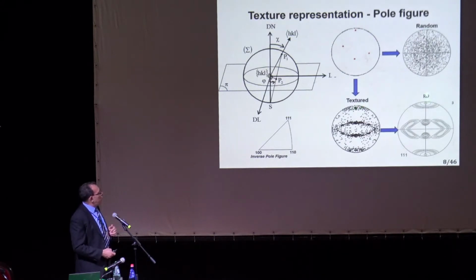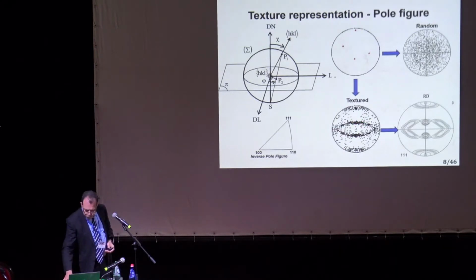For example, this is the rolling direction. This is the transverse direction, and the normal direction is in the center. So we can say that if this is a 111 pole figure, then the 111 normal planes will have some of them concentrated around the rolling direction, and some in these areas here. So I'm not going into details of this.